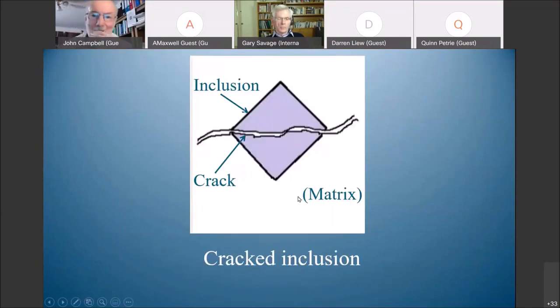So let's get on to the meat of what I really want to say today. This is the theme of my new book. And I say, let's look at this inclusion, which might be a carbide in a steel. And very often the carbides in steel sit at grain boundaries, and very often they're cracked. And the failure modes of steels are accepted nowadays as extending the cracks from cracked carbides. And so this crack goes off into the steel and causes the failure of the steel.